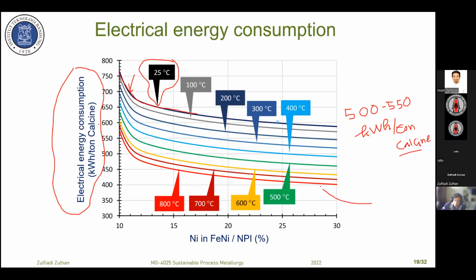And in this case, the theoretical calculation is without any losses to the environment. So we see, in this case, 500 to 550, the temperature of calcine is around 600 in this line here. In this line, the theoretical calculation depends on the grade of the raw nickel that will be produced. If we produce lower nickel content, it means that most of the iron oxide shall be reduced by carbon.